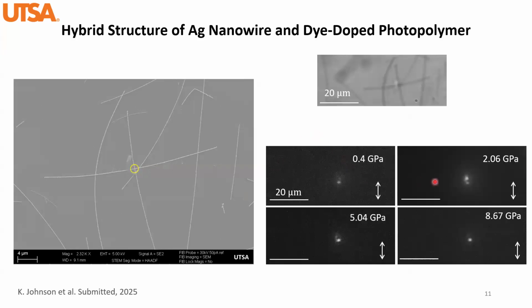At different pressures, as pressure increases, this top part of the bridge lights up at 2 gigapascals, then decreases at 5, and we cannot see it anymore at about 8 gigapascals. This tells us there might be an optimized pressure in the system, which means there are multiple processes that are probably competing with each other.